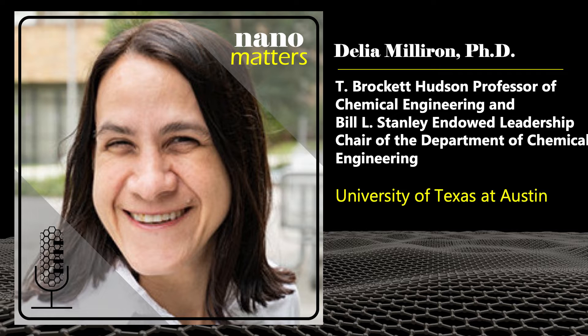So is the structure of this window film like a battery? Yes. The active material acts like one electrode in the battery, and the opposite electrode can also provide a change in tint, so they work together in a complementary fashion. What we're effectively making is a thin film battery where all the layers are spread out across the glass or window pane. When you look through the window, you're looking through the complete battery stack — both electrodes as well as the electrolyte that facilitates the switching between the different modes.